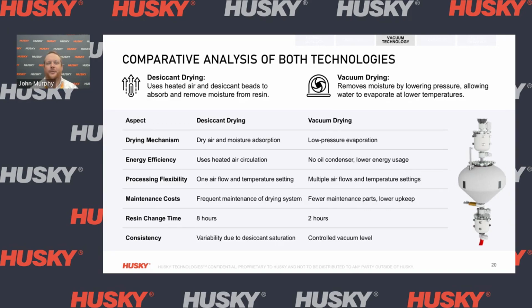Now, when we look at the vacuum drying system in comparison, the drying mechanism is quite different by using low pressure evaporation by changing the boiling point of water. When we look at energy efficiency and the processing of rPET material, there is no need for an oil condenser, which is a big advantage, reducing energy consumption significantly.